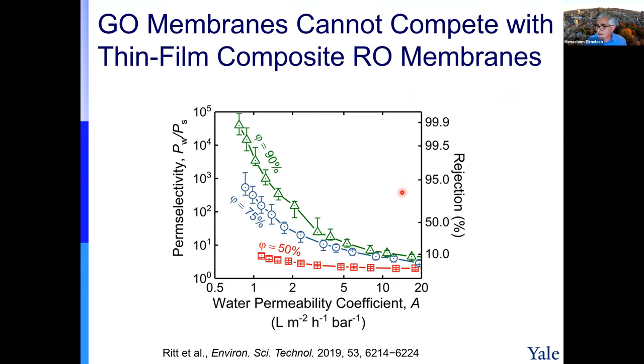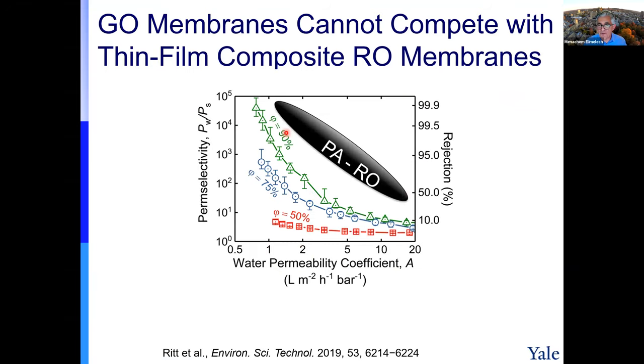Now, when you go to the current TFC polyamide membrane, they fall here. This is the current membranes. So you see that even with 90% coverage, that is almost impossible. And even under ideal condition that everything is laid down very uniformly, you will not be able to beat this polyamide reverse osmosis membrane.